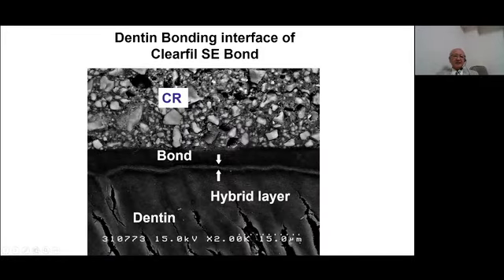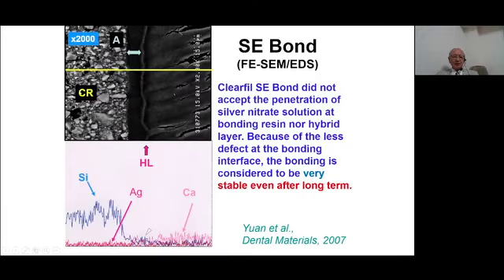Okay. Now this is the bond interface in the case of Clearfil SE Bond. Composite resin is here, bonding resin is here, and a very thin hybrid layer is observed. Even though the hybrid layer is very thin, the quality is very high, and there is no silver penetration at the bond interface. That's why this bonding is considered to be very stable, even after a long time.